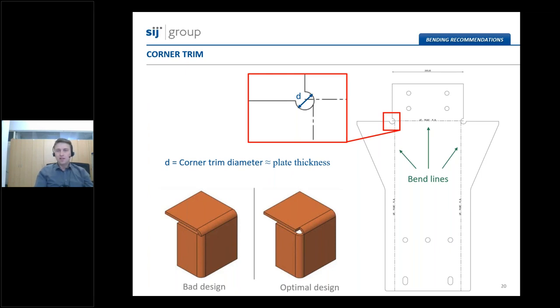And this can be effectively done with so-called corner trimming, or it is sometimes also called the edge relief trimming. So when cutting flat pattern sheet metal, we make small holes at all those line intersections. And typically the diameter of this hole is or should be approximately the same size as the thickness of the plate that we want to cut.